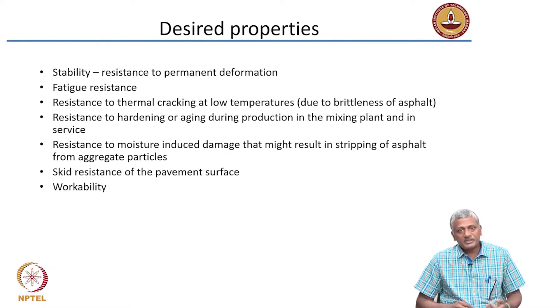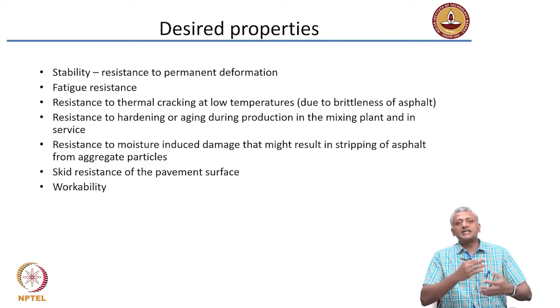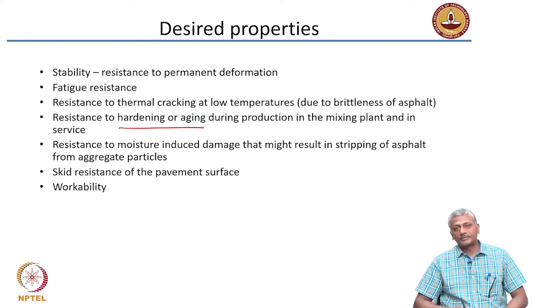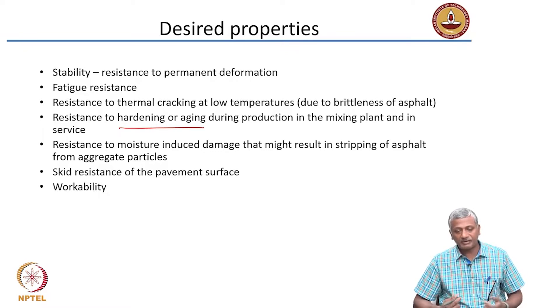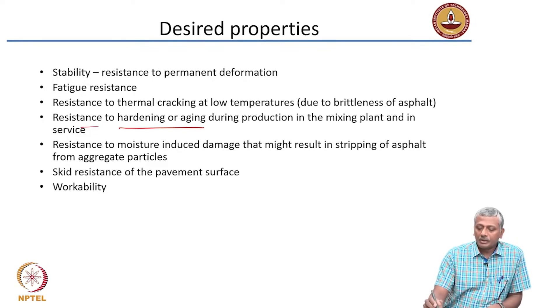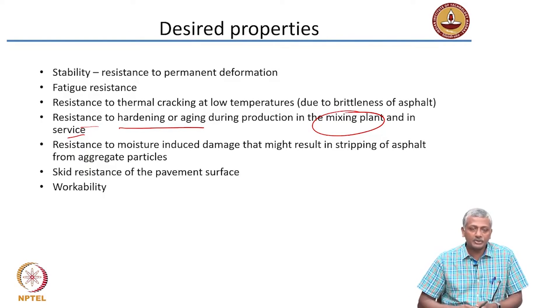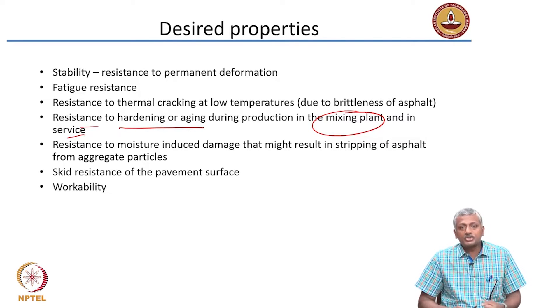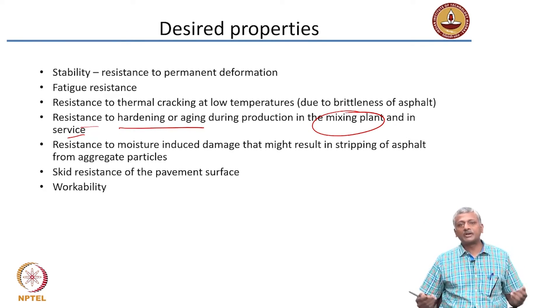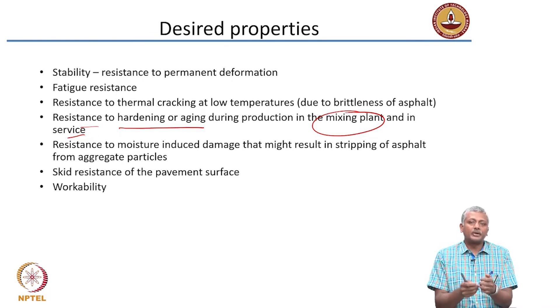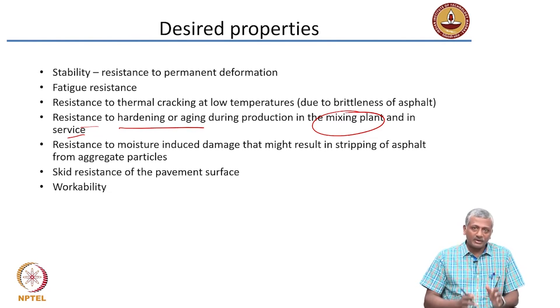Asphalt is a polymer subjected to ultraviolet radiation, and the effects of heat during the mixing process can affect its properties, leading to hardening or aging. When asphalt pavements age due to external exposure, they become less and less flexible and start cracking. Resistance to hardening applies not just in service but also at the mixing plant where high temperatures are used. Resistance to moisture-induced damage is also critical — heavy rain on improperly laid roadways can cause the aggregate to become loose and strip the bond between asphalt and aggregate.